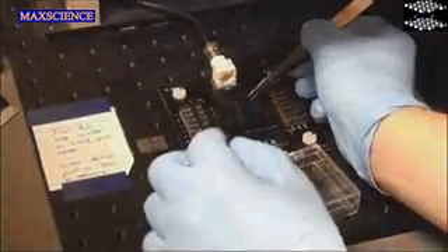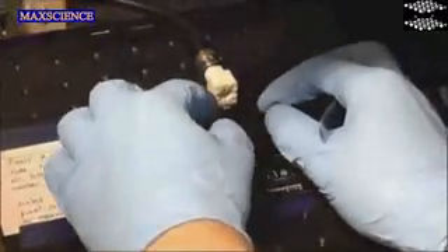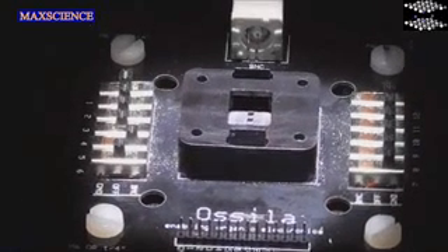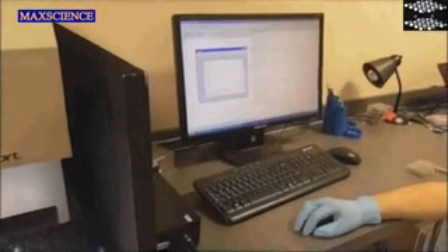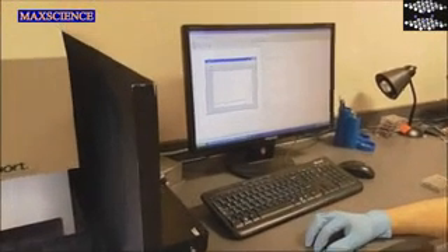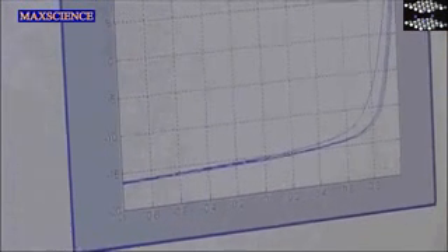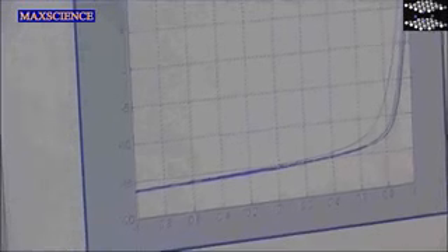Each device is loaded into a test rig and placed under the solar simulator. An aperture mask is used to restrict the active illuminated area. The efficiency of the devices is recorded by measuring a current voltage sweep as they are illuminated by the solar simulator. We routinely characterize the device open circuit voltage, short circuit current, fill factor and power conversion efficiency. Using the Ossila I101 perovskite precursor ink, we routinely obtain power conversion efficiencies greater than 10%.